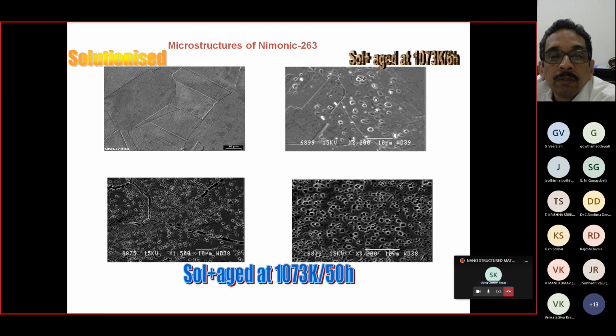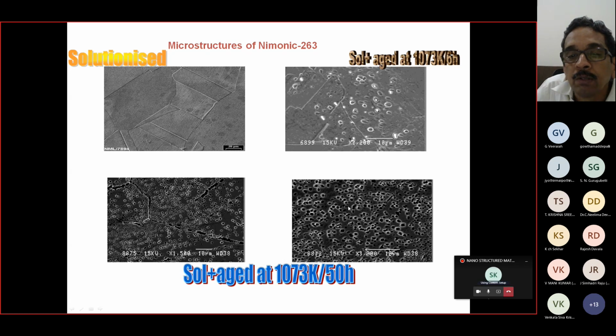As I was telling you, when we have to justify ourselves, the ultimate proof is through a microscope. Seeing is believing for all of us. Unless we see it in a microscope, we cannot believe whether we have the nanostructure or not. Even though this was done at a later stage, I am putting it in the first stage to put across to you that these black spots are nanostructured material, nano precipitates, I call it.